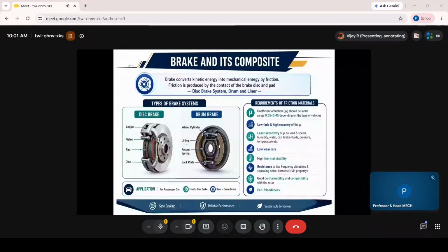So 0.35 to 0.45, that is FF rating, is generally okay, because if it's more, it will erode the disc, it will bite, which we generally call eating or cutting off. That will not happen if it's in this range. Another thing is it should have low fade and higher recovery.